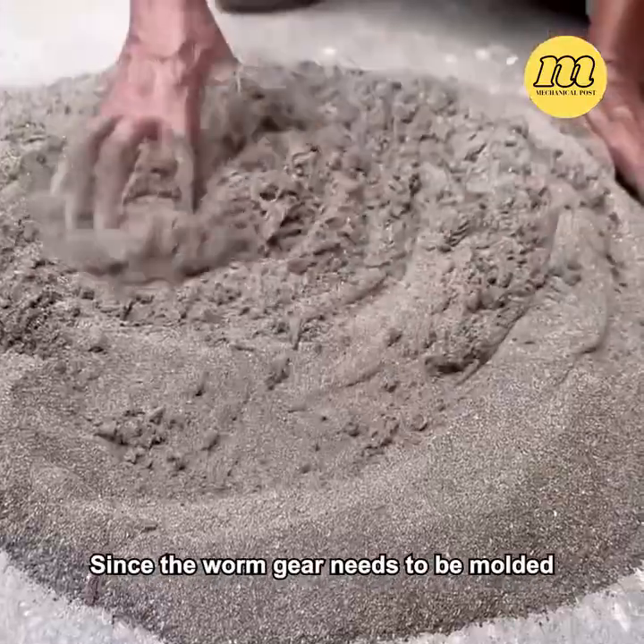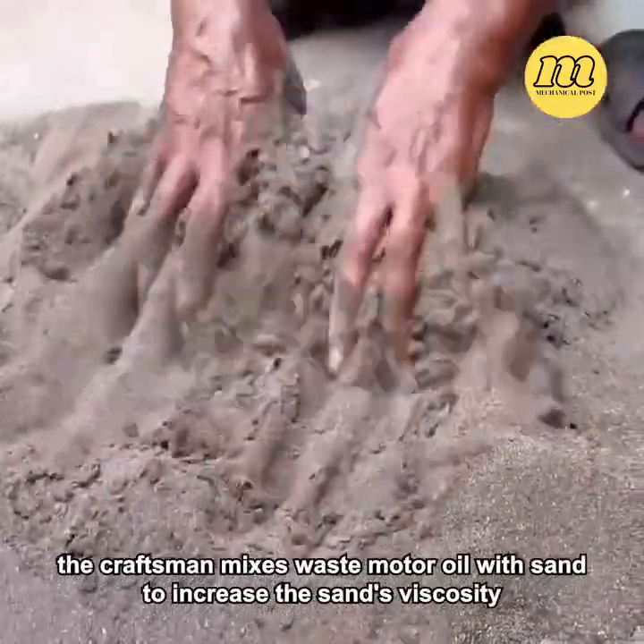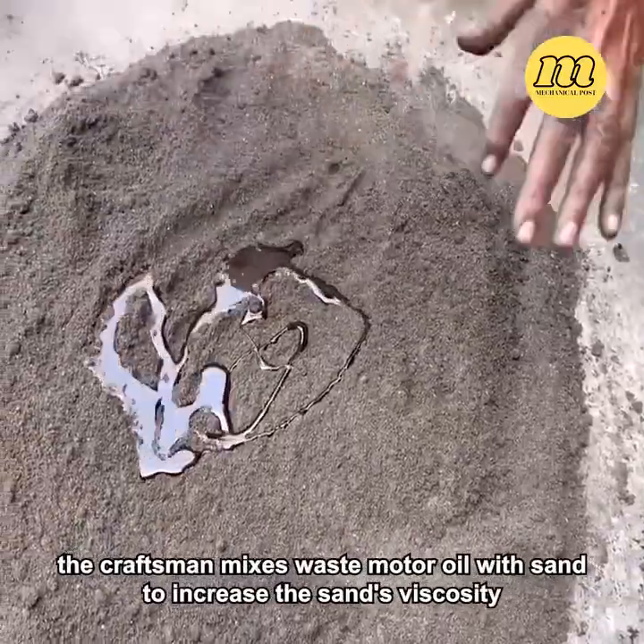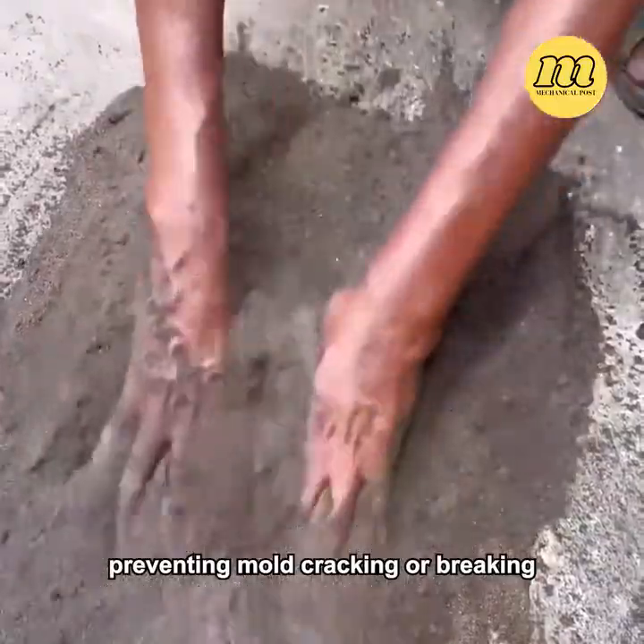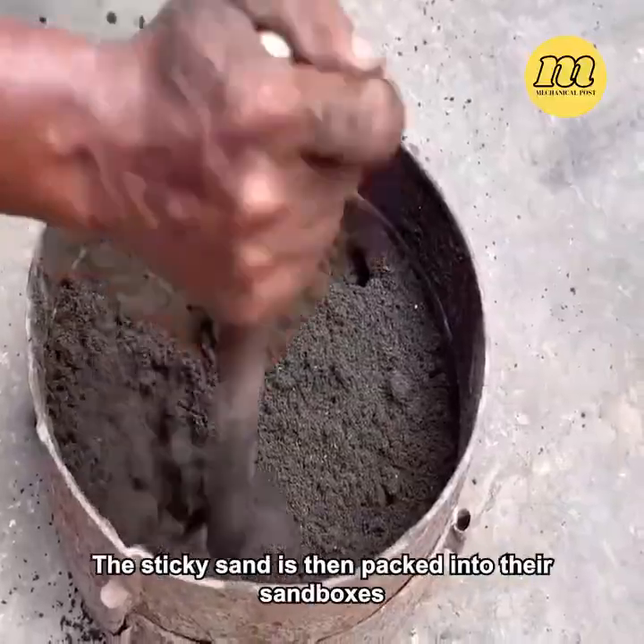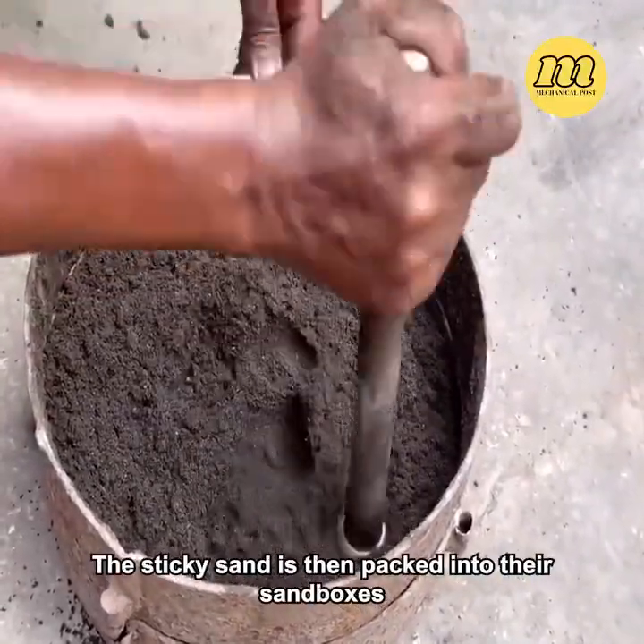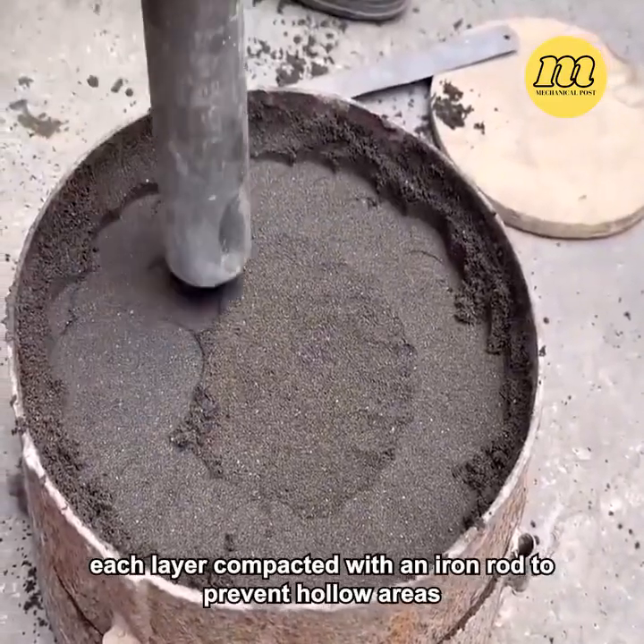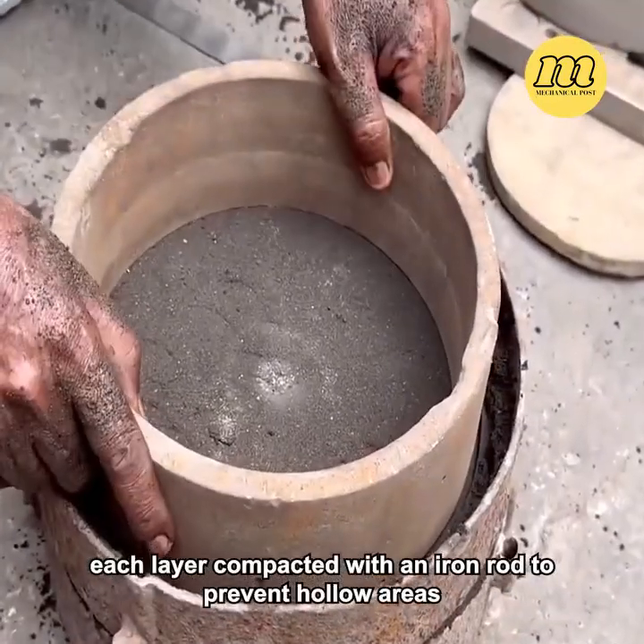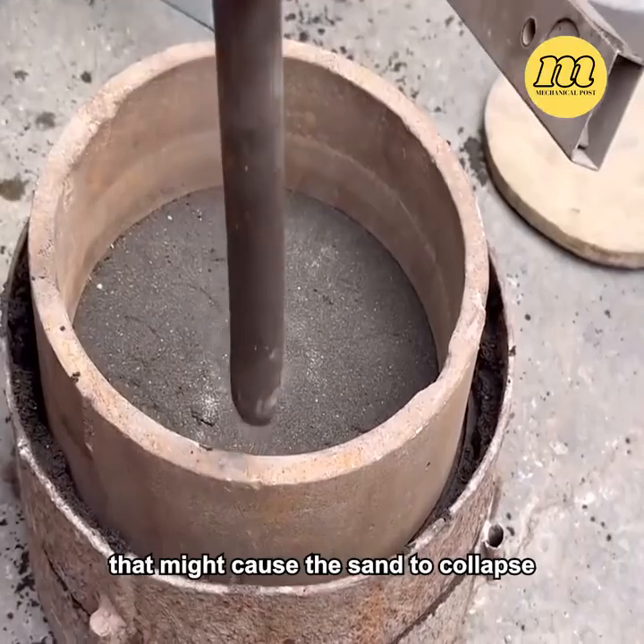Since the worm gear needs to be molded, the craftsman mixes waste motor oil with sand to increase the sand's viscosity, preventing mold cracking or breaking. The sticky sand is then packed into their sandboxes, each layer compacted with an iron rod to prevent hollow areas that might cause the sand to collapse.